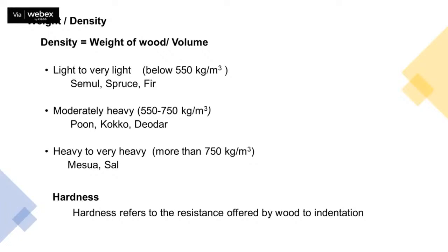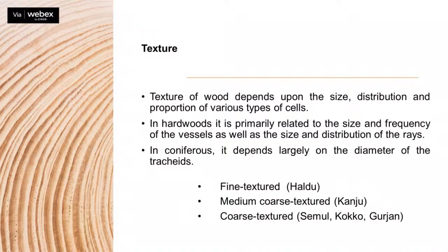The texture is nothing but how we feel the surface of a wood when we put our finger on it. As I mentioned in the previous slides, the feel depends on the texture, particularly the size, distribution, and proportion of various elements. How these cells are, what is the proportion of each element, and what are their size and distribution, they affect the feel. In hardwood, it is primarily related to the size and frequency of the vessel cells, and the size and distribution of the ray cells.